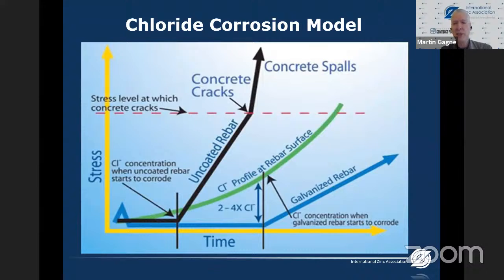So it takes us much longer to initiate the corrosion, and then it takes much longer for the zinc to be consumed or for any stress to build up on the bar. Eventually the zinc will be consumed and the black bar will start to corrode. But this is what gives us such phenomenally long life using galvanized rebar compared to uncoated black rebar.